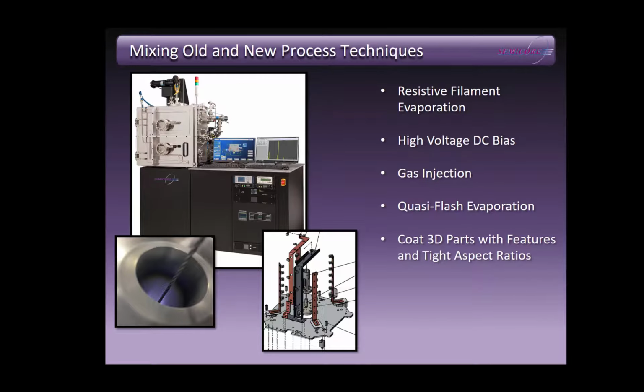This customer needed to coat several different large three-dimensional parts with many features cut in it. Some of those features had very tall aspect ratios, making it difficult to get deposition where it needed to go. Utilizing some creative filament evaporation techniques initially pioneered by the customer, we modified the approach and added high voltage DC bias on the part. Very high voltage. That coupled with adding an inert non-reactive gas and controlling the process pressure much higher than typical evaporation processes do, we were able to achieve the coating requirements with better than expected homogeneity.